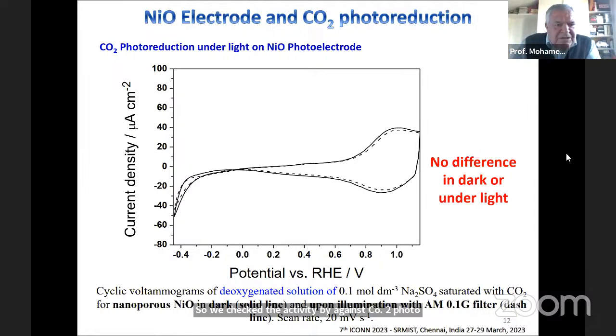And we start with the nickel electrode. As you can see, the nickel electrode is not really active when under light and in dark. The same current is measured for this electrode in both cases, for a solution of Na2SO4 saturated with CO2, degassed from oxygen and saturated with CO2. As you can see, there is no difference. Next slide, please.